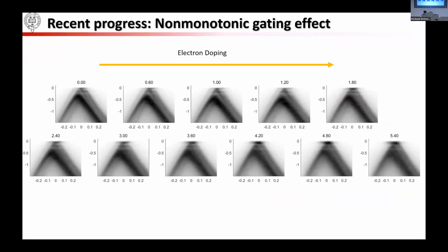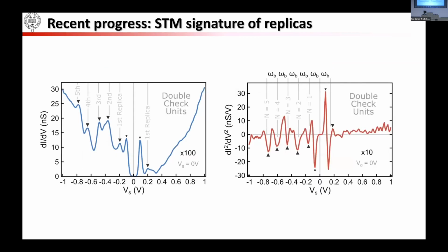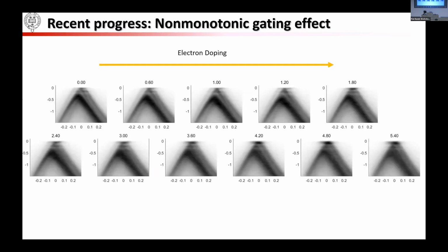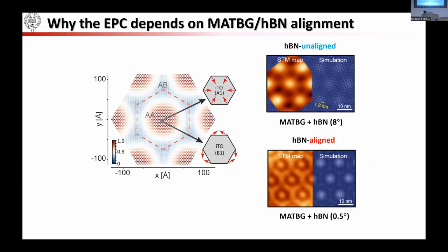We saw that upon gating, this replica intensity doesn't change monotonically. This is another proof that this intensity is not caused by band hybridization. If it were caused by band hybridization, it wouldn't really matter what filling you have. I think this is an indication that this is really caused by the flat band, and electron correlation does play a role here. So this is the data. We just got it on Monday. Okay, thank you. Well, we have to cut.